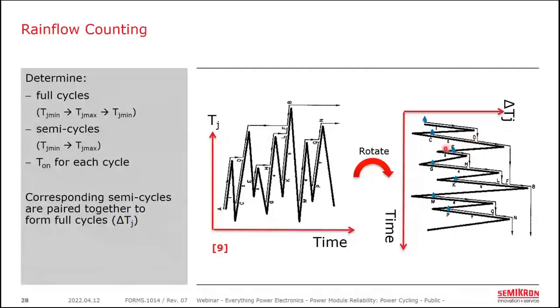And you take those semi-cycles and you can match them up if they have corresponding values or corresponding deltas. And you end up with a big list of delta TJs, heating times or T on times for each cycle, and maybe some remaining semi-cycles at the end. And so, as you can imagine, this is a relatively complex process, and you don't do this by hand. Typically, you do this with a dedicated computer program or an Excel or Python program that looks through the data.